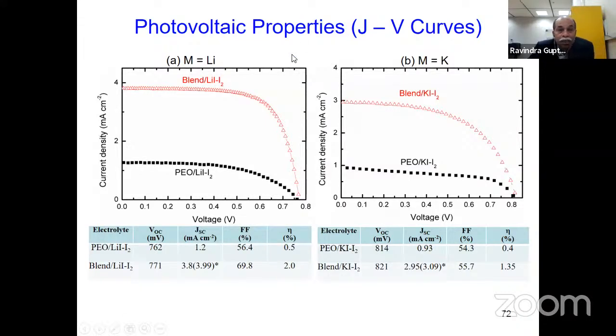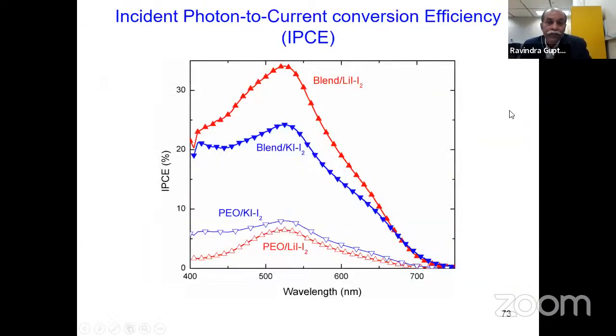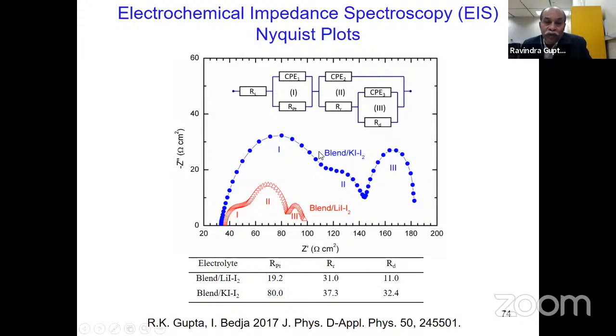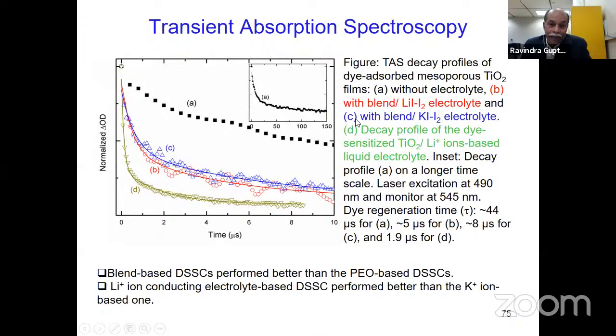But here you can see efficiency. In my case, when I use PEO, efficiency is very, very low because of the interfacial problem. We don't have very good connectivity between the TiO2 dye and electrolyte. This is the problem. That's why when we use succinonitrile, it helps, but still you can see efficiency is not good. The problem is the interfacial connectivity. And these are the IPCE spectra. It's very, very good. You can see. Then we model it, this Nyquist plot, and then we get the resistance. Like that, we do some extra work.